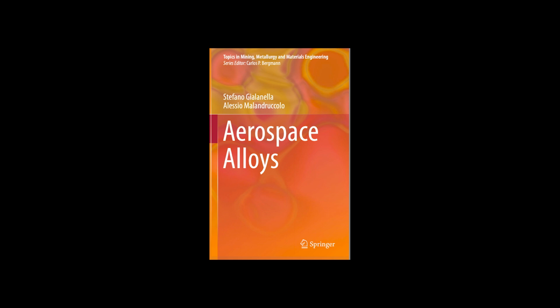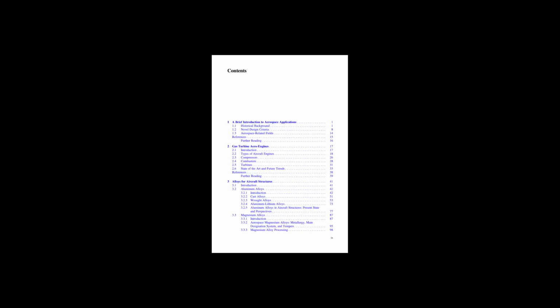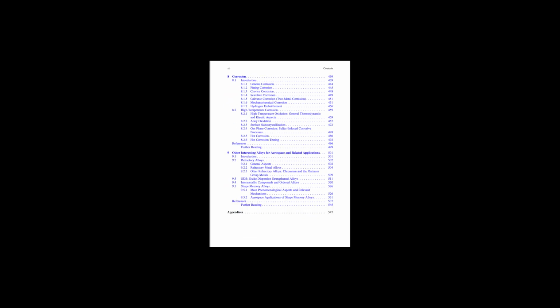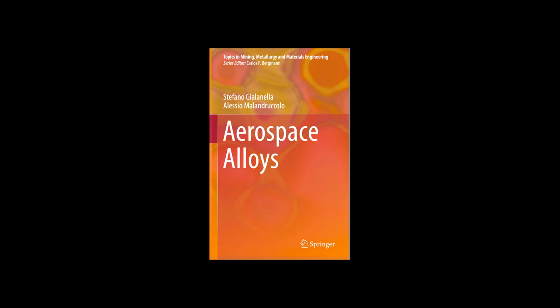What does the yttrium do? It dramatically improves the adherence of that protective alumina scale to the coating, preventing it from spalling off during temperature changes. MCrAlX coatings are generally more ductile than simple aluminides and offer more flexibility in tailoring the composition for specific needs. They are often applied by thermal spray or PVD. Do these coatings interact with the superalloy underneath? Yes, there's always some interdiffusion over time at temperature. A zone called the SRZ, secondary reaction zone, can sometimes form.